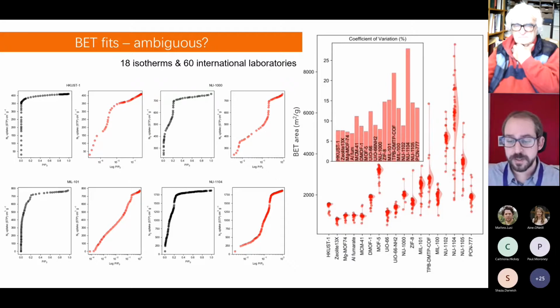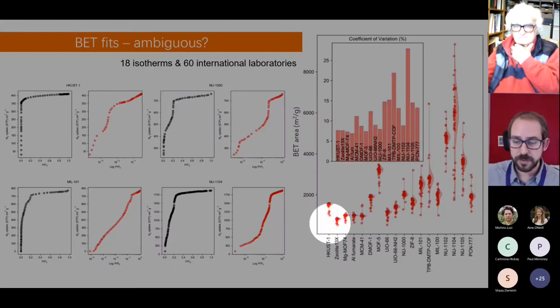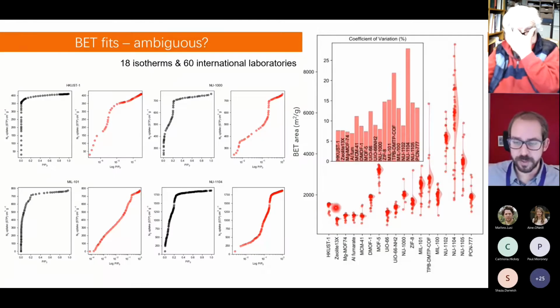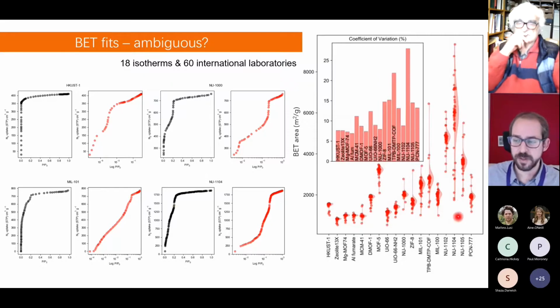And for some materials like the HKUST-1 that you can see here, most of the people were giving similar results, no problem, some deviations, but most of the people were fairly clustering around specific values. But then we were going for more complicated isotherms, and then you can see this for a COF, covalent organic framework, a lot of deviation. And then if I go to this material that you have here, you look at this dispersion of data, okay? This is the results from 60 different labs.